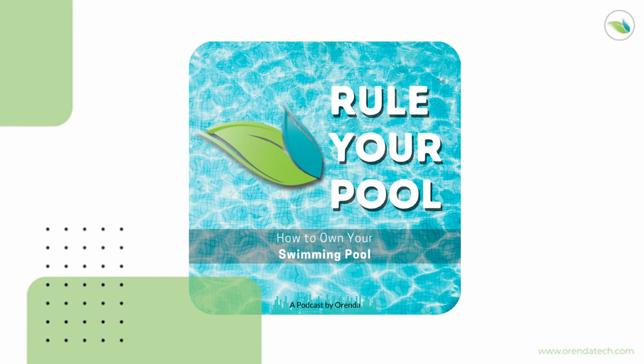So in summary, there are two very different opinions on what initially causes the weakness in plaster to allow nodules to exist, but there's no disagreement that it is minerals from within or behind the cement coming to the surface. And how to stop it? You probably need to resurface your pool. You can sand them off, you can hide them, you can try to dissolve them, you can do all sorts of stuff to band-aid the problem, but realistically, in our experience, you almost always need to waterproof that shell.